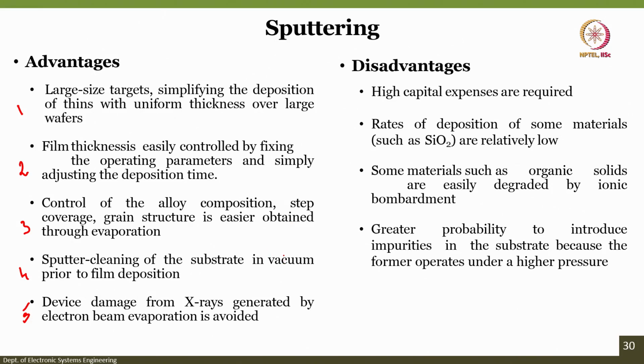But then, what are the disadvantages? The first one is the high capital expense. Second, the rate of deposition of some materials is extremely low, like silicon dioxide. We use RF for insulating materials. Some materials such as organic solids are easily degraded by ionic bombardment. This is an important parameter, number three, that is a disadvantage. And the last is the greater probability of introducing impurities in the substrate because sputtering operates under high pressure. This is also a very important thing when we are using sputtering compared to e-beam or thermal evaporation. So let's see the next slide.